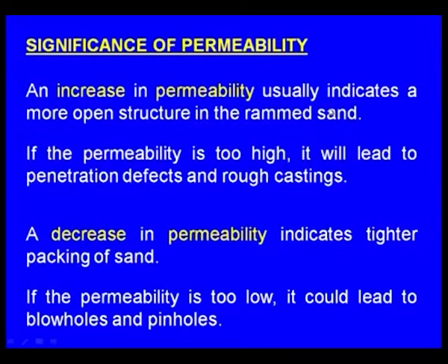If the permeability is too high, then what will happen? It will lead to penetration defects and rough castings. Naturally, when the permeability is too high, the sand grains are not compacted very tightly, they are loosely compacted, meaning between the neighboring sand grains there is a large clearance. Now we pour the molten metal, and its viscosity is very less because of its high temperature. It can penetrate anywhere, and it penetrates into the clearance between the neighboring sand grains, goes inside and makes a fin. This is the penetration defect.